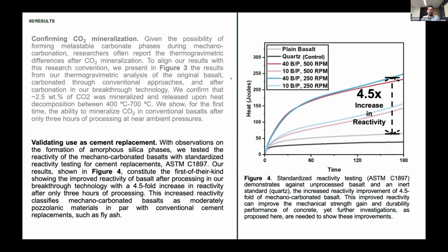Now, when we're looking at cement replacement performance, ASTM C1897, or the R3 test, is one of the key testing techniques that we have to understand whether a material is going to be reactive or not. In other words, it tests whether a material could be used as a cement replacement, or is just going to be an inert filler. In the results here in Figure 4, when we compare to plain basalt without any mechanical carbonation, we see that at 40 ball to powder ratio, we actually increase the reactivity by almost 5-fold.